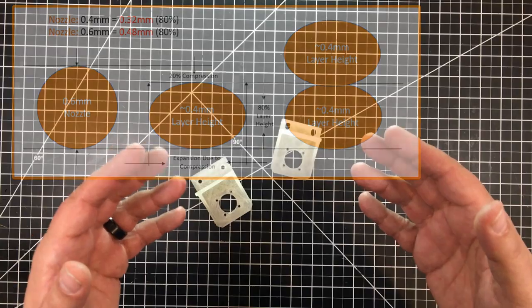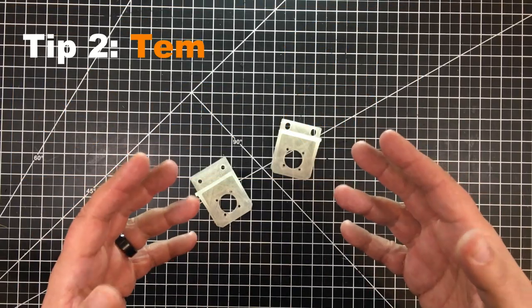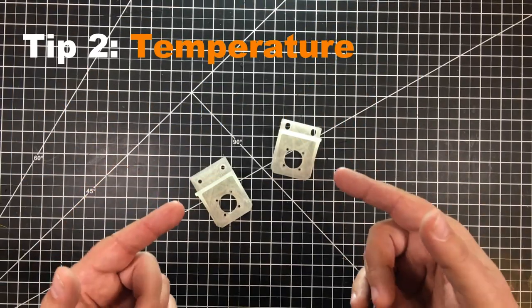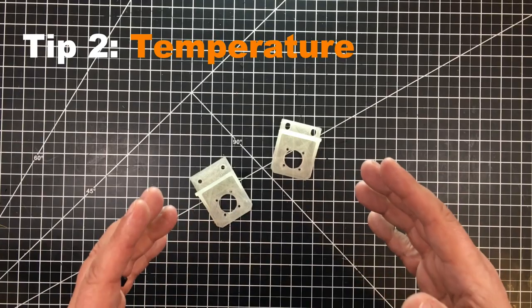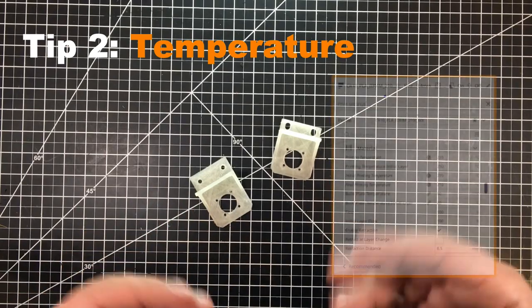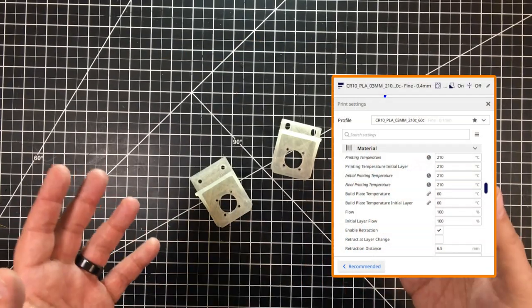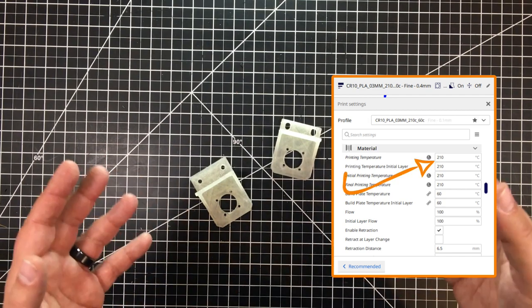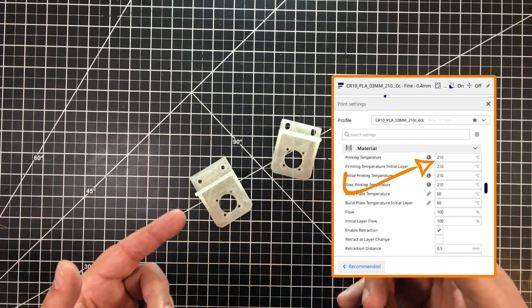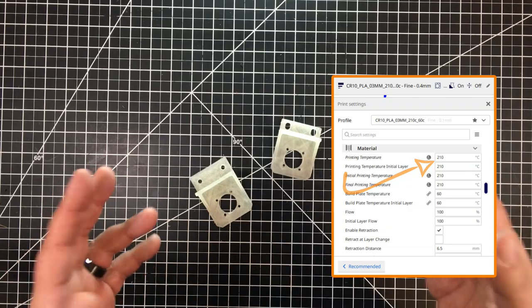The second tip is temperature. I print hotter when I do something like this than I do for normal prints. So if I typically print at 205, I'll probably print around 210. You can do some experimentation. I found usually for PLA, going about another 5 really helps.